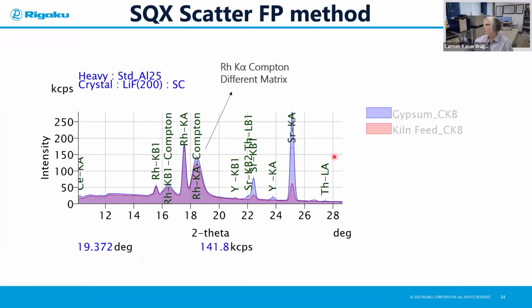Here you can see, for example, the analysis using the Compton. This Compton line will have an influence based on the different matrix. Here we have an example of gypsum and kiln feed. These are natural materials, from the mining process. Kiln feed is a mixture of clay and sand and limestone and bauxite, for example. Those 4 components are part of a kiln feed. And of course, because they have different matrices, they have a carbonate portion, they have a crystal water portion, and these portions are picked up by the Compton line. So we can estimate this balance very easily.